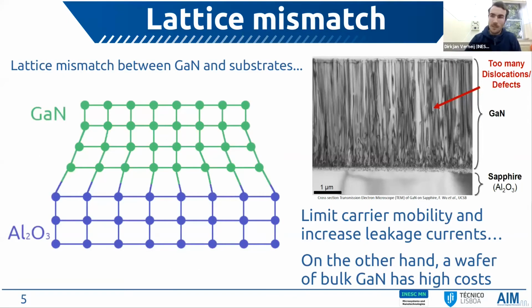However, there are also some problems with gallium nitride, and one of these problems is that it is relatively difficult to grow gallium nitride epitaxially, or rather, difficult to grow high quality gallium nitride. This is because of the lattice mismatch between gallium nitride and a typical growth substrate, which I show here in this schematic. So here we have a sapphire substrate, and the mismatch between the gallium nitride and the sapphire, which basically means that the material does not fit well on the substrate, creates a strain in the crystal lattice, and this strain leads to a very high density of dislocation defects.